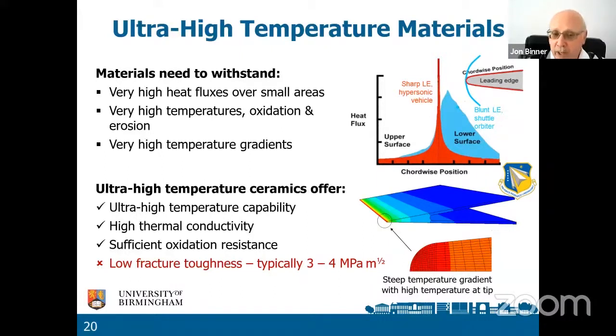So the materials that we're looking at are ultra high temperature ceramics. They have the ultra high temperature capability. They have a high thermal conductivity, which is very good because it helps to dissipate the heat. And they have adequate, sufficient oxidation resistance. It would be better if that was better, but it's okay. The big disadvantage of these materials is they have a very low fracture toughness, 3 or 4 megapascal meters to the half. That's about the same as alumina, and that's just not good enough.